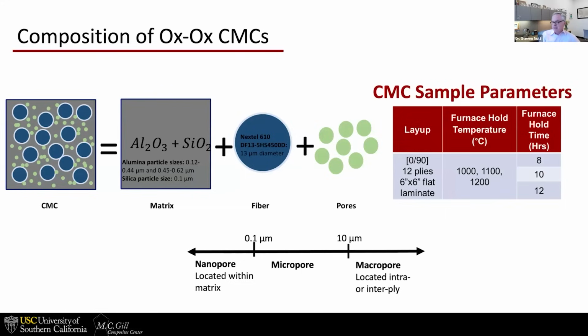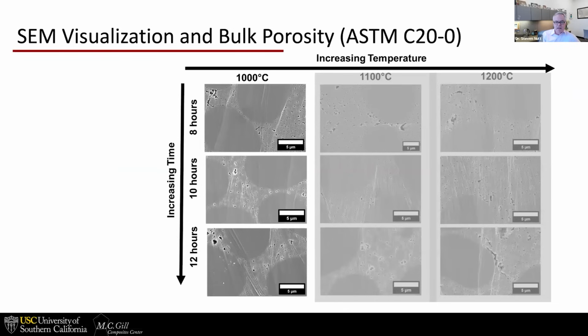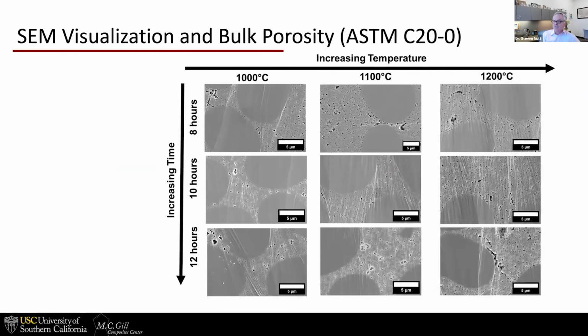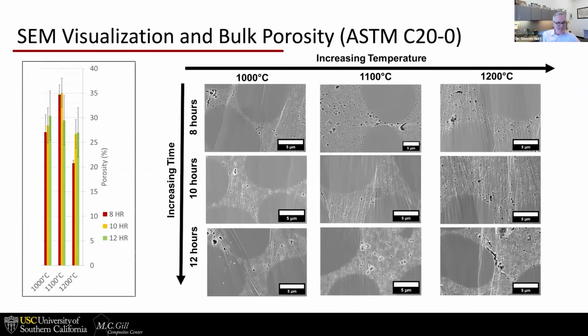Now, sample preparation, typically a 10-hour production cycle, temperatures of 1,000 to 1,200 degrees C. This is a series of micrographs showing increasing sintering time top to bottom, and left to right is increasing sintering temperatures. And you can see these are kind of difficult measurements to make because porosity is an elusive and multifaceted quantity. So it's a lot of scatter. Here, 8, 10, 12 hours at 3 different temperatures and not a whole lot of difference. And large error bars on all the measured values, but you can see porosity in each case is upwards of 20%. This is not polymer composites where you reject parts because of more than 1 or 2% porosity. This is what flies on engines with 20+% porosity.